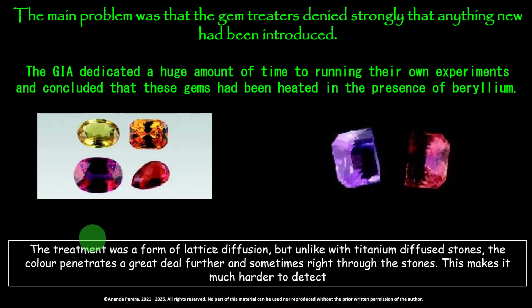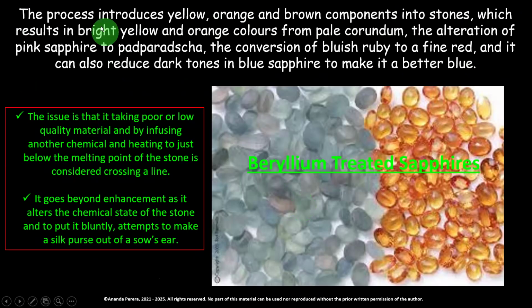The treatment was a form of lattice diffusion. But unlike with titanium diffuse stones, the color penetrates a great deal further and sometimes right through the stone. This makes it much harder to detect because the complete gemstone is filled with beryllium ions. So the color is established everywhere evenly. Here, the process introduces yellow, orange, and brown components into stones, which results in bright yellow and orange colors from pale corundum.